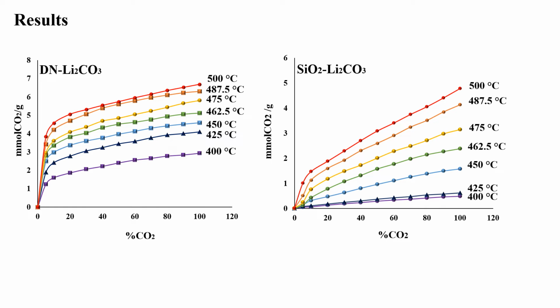Coming to our results, as shown in the two figures, each one presents the amount of carbon dioxide adsorbed at various flow compositions from 0 to 100% of CO2 in N2 over the two elaborated materials in the range of 400 to 500 degrees Celsius. The results show that the amount of CO2 adsorbed over both elaborated materials increases with temperature, indicating the chemical nature and revealing the endothermic nature of interaction between the CO2 molecules and the lithium silicate obtained. Furthermore, for the two elaborated materials, 500 degrees Celsius achieves the highest CO2 adsorption capacity.